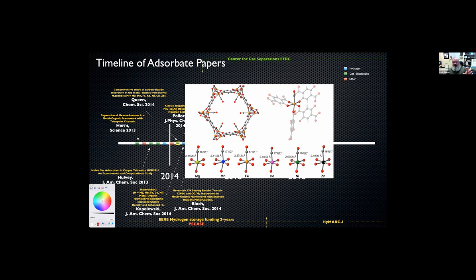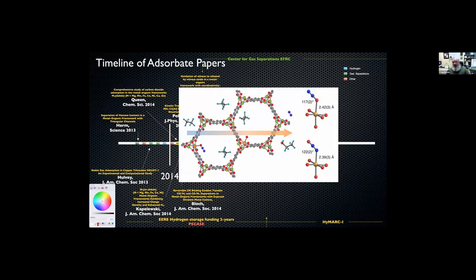You can characterize the degree of backbonding and orbital overlap by how close the CO2 molecule is getting towards the transition metal and also how far away from 180 degrees it is. The same concept applies in this case where Diane was absorbing N2O into the same series of metal organic frameworks, and using the weak oxidative properties of N2O to convert ethane into ethanol. And Wendy did some work trying to understand the differences between the different adsorption states. And you actually get both types of binding mechanisms inside this metal organic framework. It's only the O-bound one that seems to be functional, however.